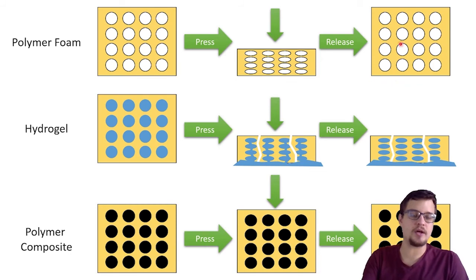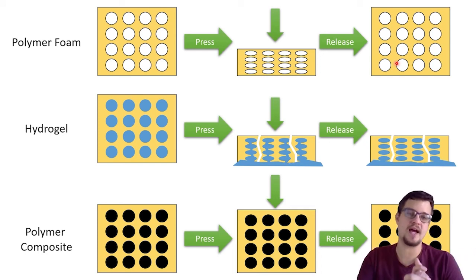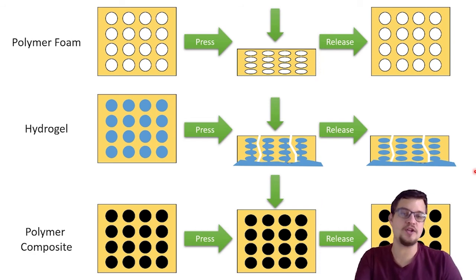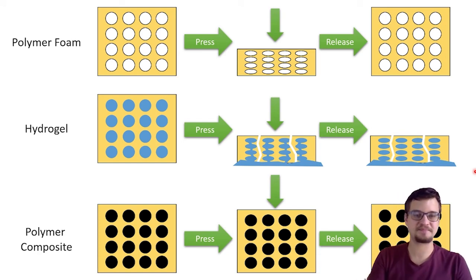And then we can think about what happens when we remove the force from our materials. So we saw with our polyurethane foam, as soon as I stopped touching it, it would spring back. And we know this for any foam or sponge. The pores will come back and they refill with air. With our hydrogel, because the polymer matrix is typically very weak, it doesn't tend to spring back. It doesn't tend to draw back the water. And usually we end up with that structure damage being permanent.